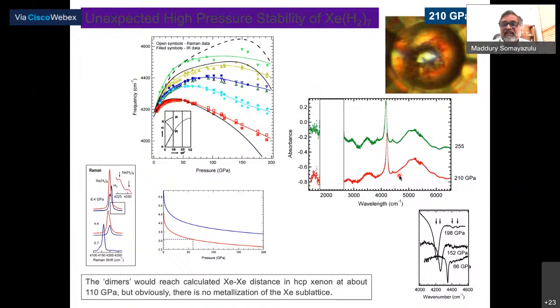And what you find is there is nothing in the infrared which is even remotely suggesting any metallization in this material. And not only that, what was more intriguing to us was that if you calculate the xenon-xenon distance based on the volumes which we observe, the xenon-xenon distance shows dimerization. Not only that, xenon itself metallizes around 150 GPa, but that distance is achieved at fairly low pressures. In other words, the metallization of the xenon sublattice within this compound does not do anything.